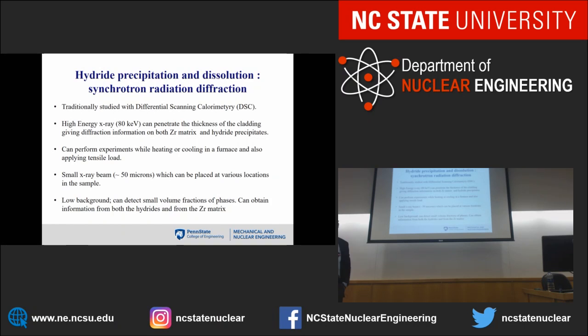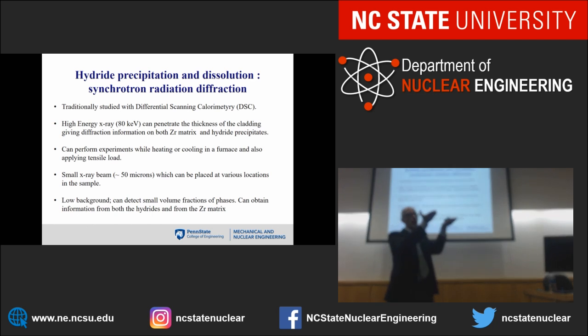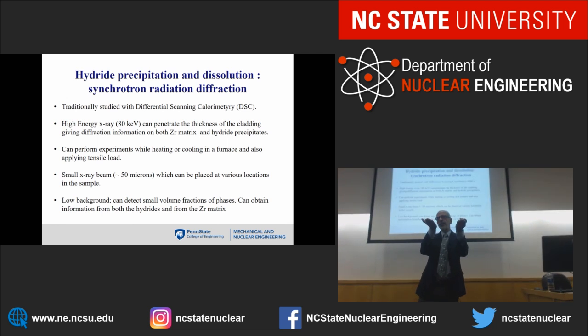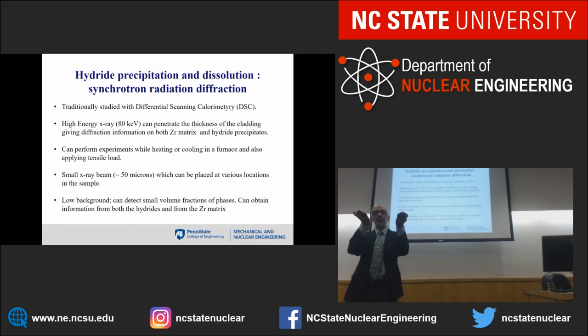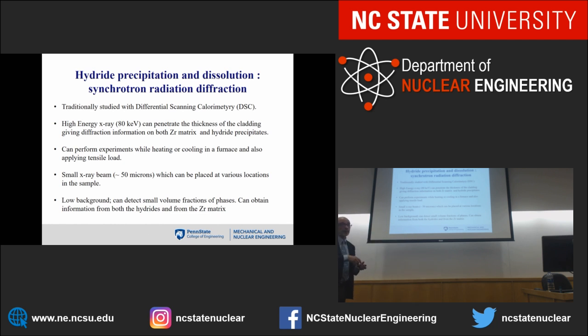So we have studied this more closely using synchrotron radiation diffraction. This is traditionally studied using a process called differential scanning calorimetry. Basically, I heat two samples, and one of them has a hydride in it. As I dissolve or precipitate the hydrides, if it's an exothermic process, it will emit heat, and I have to calibrate in order to make the temperature of the two the same. I have to calibrate the heat in this sample so that I can measure the heat of reaction that way. Well, in this, we can also do